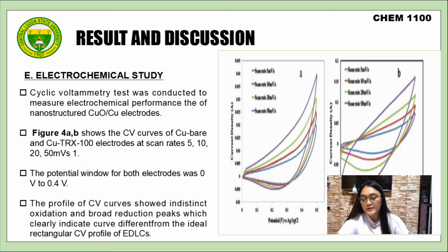For the electrochemical study, a cyclic voltammetry test was conducted to measure the electrochemical performance of the nanostructured copper oxide on copper electrodes. Figure 4A and B show the CV curves of copper bare and copper TRX100 electrodes at scan rates of 5, 10, 20, and 50 mV/s. The potential window for both electrodes was 0 to 0.4 volts.